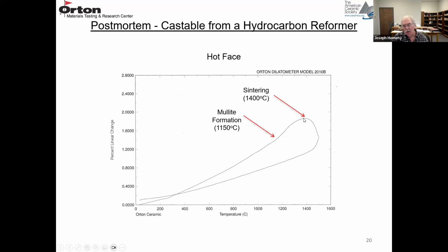And if you continue heating, you see that it starts to bend over and shrink. Well, that's where the sintering process, the densification process takes place. And that's at 1400 degrees C. So that's way beyond mullite formation. So obviously the refractory didn't see this kind of temperature. And then you see it cools down, and then it follows a pretty linear slope. So all the mullite has formed. You don't see a slope change on cooling. So thermal expansion can be useful on an unfired refractory for doing some type of check on what might be the maximum temperature that the refractory saw.